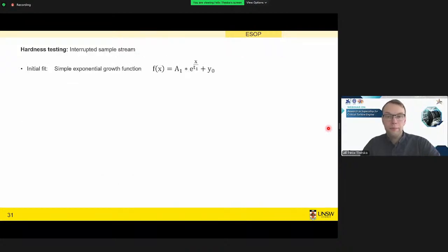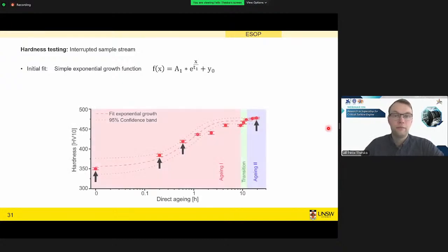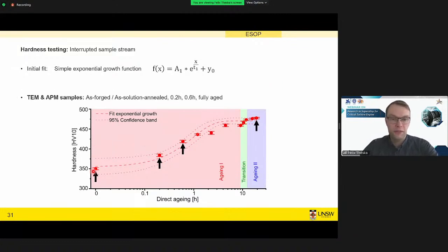And what we can do with these samples once we have heat treated them is do some hardness testing. As you see here, over the direct aging time, the hardness profile roughly fits an exponential growth function. We do see some outliers after 2 hours, in the transition, as well as in the aging too. But to really understand how these initial stages of the precipitates form, we selected these samples highlighted by the black arrows. So the as-forged, 0.2 hours, 0.6 hours direct aged, and then fully aged.